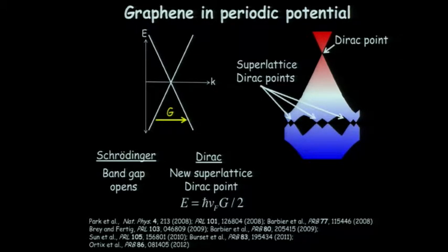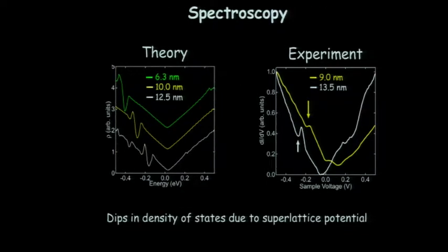There is an interaction there with some periodicity given by the Moiré pattern wave vector. And that's going to then cause the normal Dirac cones to get these new superlattice Dirac points at a wave vector that's associated with the Moiré. So by changing the rotation angle, that changes the wave vector here. That moves it up or down in energy. And you get these new dips in the density of states as a function of energy.